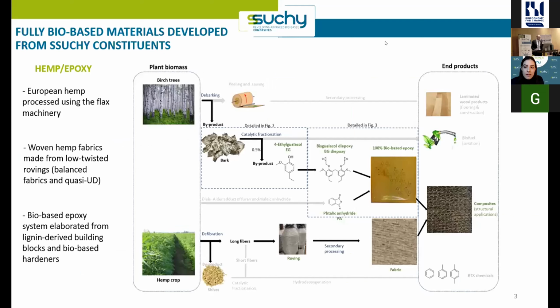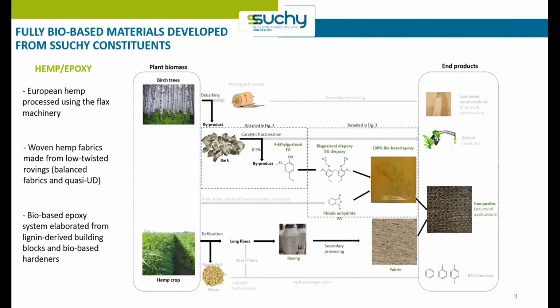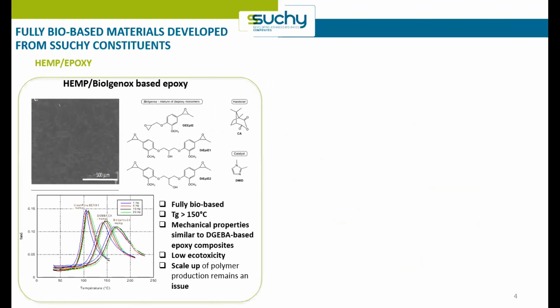So on the next slide, I will show you what we obtained with the 100% sushi composite material, so mixing together the developed bio-based epoxy and the developed fabrics. So I reminded here the value chain, and on the next slide, you can see the two composites that were developed, one based on hemp fibers and Biolgenox. So Biolgenox is the first fully bio-based epoxy used in the project from isoeugenol coming from biomass. So we obtained at the end a fully bio-based composite with a Tg higher than 150 degrees, mechanical properties similar to GEBA-based epoxy composites, with a low ecotoxicity.